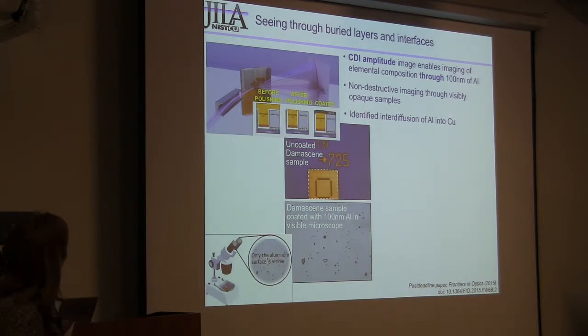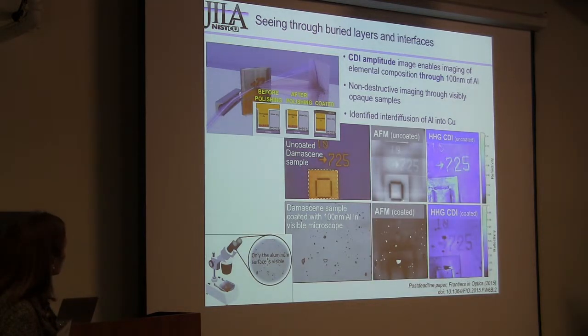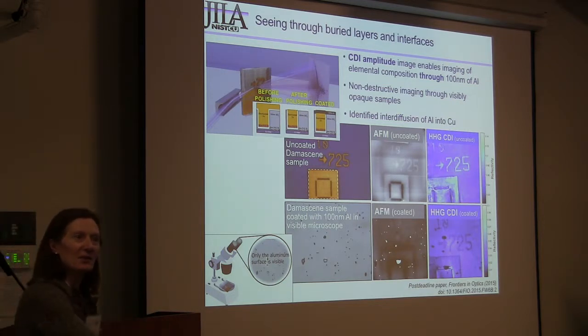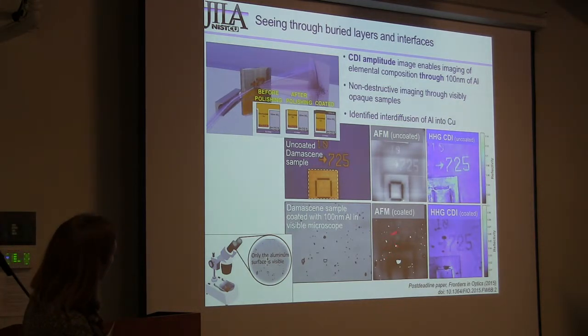Now, one thing I need to tell you before I show you the other images is that they make little vias in the TEOS, and then they coat with copper, and then they polish, but they're never able to polish perfectly flat. So the copper areas are often bumped up by a nanometer compared to the other area. And they rely on that often because they can still see with an atomic force microscope, because that can see the little bump very easily. So you can sort of see the image here. This is the uncoated atomic force microscope image, and this is the coated atomic force microscope image.